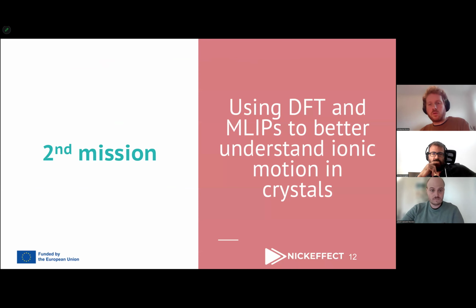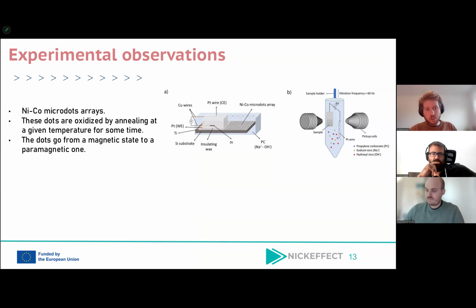Now, the second mission that we pursued within NICKEFFECT was about using density functional theories, actual simulation, and machine learned interatomic potentials to better understand ionic motions in crystals. And so it was again work that was done with the University of Barcelona. In this case, they were depositing these nickel cobalt microdots arrays, and they were oxidizing the dots by first annealing at a given temperature for some time. And so the dots were actually getting oxygen and going from a magnetic state to a paramagnetic state.